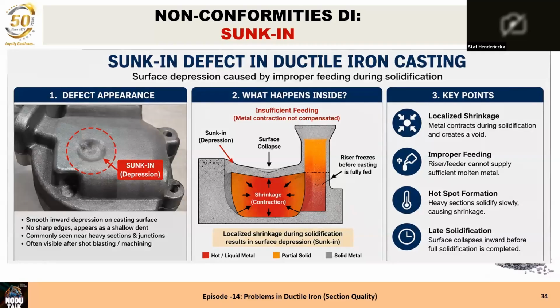You can see it in the center picture. It's happening when the outside of the section is solidified, and there is a layer of solidified metal. The liquid metal in between decreases in temperature, solidifies more, and decreases in volume, and normally when the surface stays flat, a vacuum forms, and the vacuum is so strong that it will suck the upper solidified section down, and you will see a smooth, small or bigger sunk-in defect. When the remaining section is still sufficient for the customer, it's no problem, but sometimes the remaining section is not sufficient anymore.